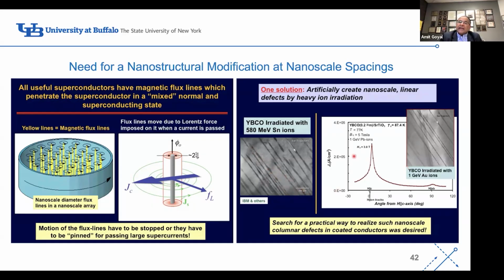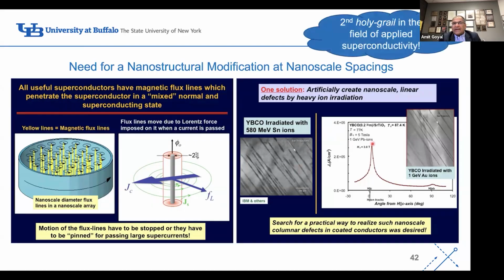So when you do that, and you again measure the amount of current you can pass through the superconductor as a function of angle of the magnetic field, when the magnetic field was aligned parallel to these lines, you got this tremendous increase in the amount of current you could carry. The question was, how can you do this in a kilometer-long wire? Oh, and by the way, without adding any cost. Of course, you can't do heavy ion irradiation because that would be very expensive, very slow, and it would make the metal substrate radioactive. That was not an option.